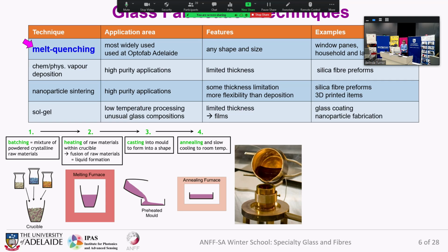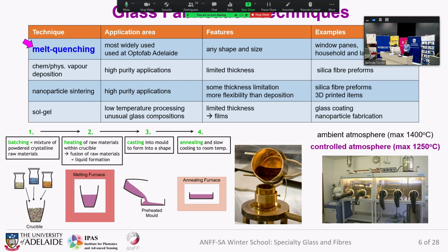And then once the glass is cast, it goes into an annealing furnace to slowly cool down to room temperature to avoid the glass cracking. Now at OptoFab Adelaide, we have furnaces that operate in ambient atmosphere, and we can go up to 1,400 degrees Celsius. But in particular for fluoride glasses and mid-infrared glasses, we have the facility to melt them in controlled atmosphere, where we can go up to 1,250 degrees Celsius.